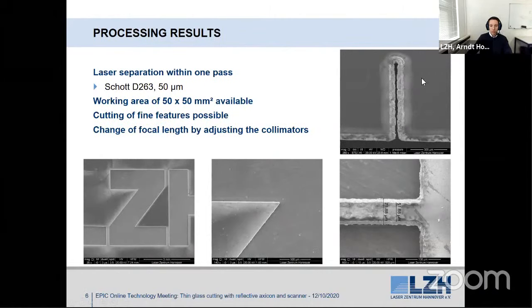To give you a glimpse of our results, you can see our cutting techniques by one-pass cutting with a femtosecond laser source by Amplitude. Here we are using 50 micrometer thick glass, and we could do it on the whole area. Fine features are possible, of course, by cutting off these glasses. As you can see in the bottom right picture, we have a transformation area. We're just at the beginning of our research, but here you can see that a boundary effect of about 5 micrometers is visible. This, of course, has to be enhanced. And we are open for collaboration in different fields, of course, and I'm open for questions.